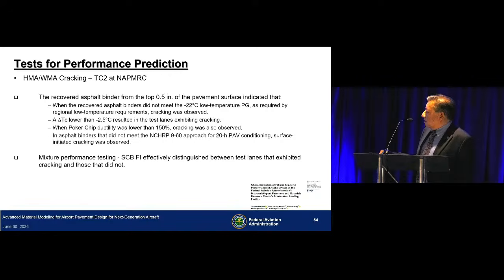When poker chip ductility was lower than 150%, cracking was observed. For asphalt binders that did not meet the NCHRP 9-60 approach for 20-hour pressure aging vessel conditioning, surface-initiated cracking was observed. Again, all the cracks that we observed in NAPMRC in these warm mix asphalts were top-down cracks or surface-initiated. We also performed tests on mixtures, and the semicircular bending test that gives you flexibility index effectively distinguished between test lanes that exhibited cracking and those that did not.